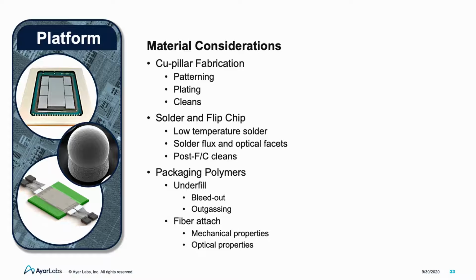Starting with copper pillars, we need processes and materials that enable copper pillar fabrication on V-groove-enabled wafers. This includes photoresist technology that can deal with high topography surface, plating technology that prevents contamination of the V-groove and spot size converter region, and cleans if necessary to ensure good performance of the fiber coupling.